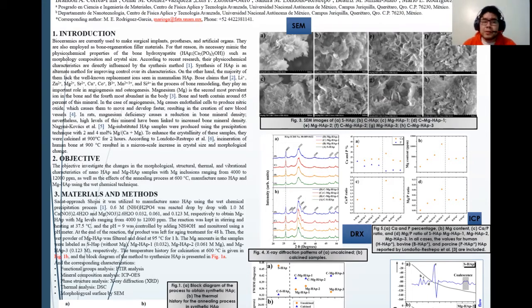And now in the inductively coupled plasma, where I studied the effect of the magnesium addition on the calcium and phosphorus ratios, the hydroxyapatite samples with magnesium exhibit lower calcium and phosphorus percentages regarding synthetic hydroxyapatite without magnesium, which is directly related to the magnesium inclusion in the hydroxyapatite lattice in calcium sites. However, human hydroxyapatite, bovine hydroxyapatite, and porcine hydroxyapatite exhibit lower values than the pure synthetic hydroxyapatite. And hydroxyapatite with magnesium presents calcium and phosphorus levels similar to the mammalian hydroxyapatites.